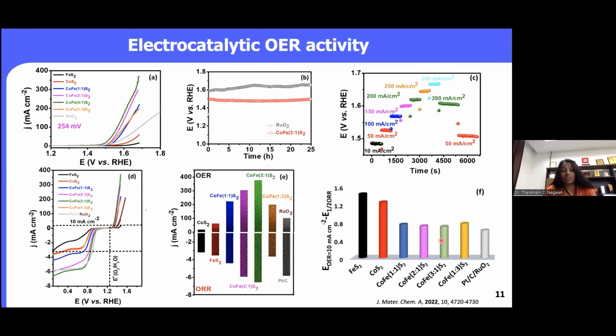So now, since we are aiming at the oxygen bifunctional catalytic activity, it's important to understand the activity with respect to the oxygen evolution reaction. Again, we perform the experiment under the similar condition only with respect to the oxygen evolution reaction. As you can see here, there is an increase in the oxidation current. This is due to the oxygen evolution reaction, and compared to the other variants, again, 3:1 stands out to be the best, and the potential required for 10 milliamp per centimeter square is only 254 millivolts, and the activity is better even compared to the ruthenium oxide.